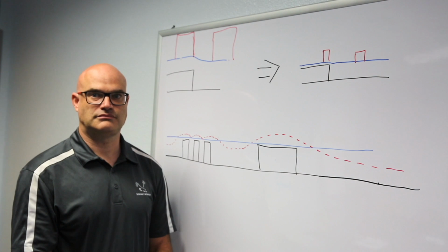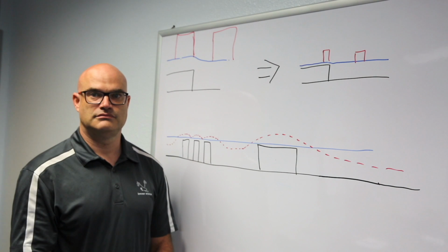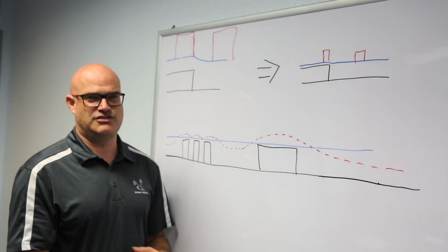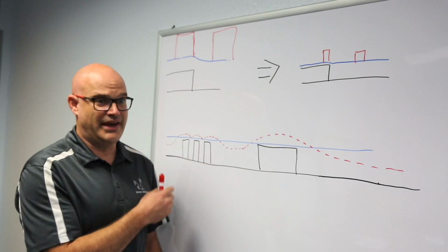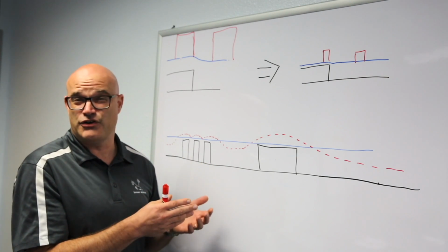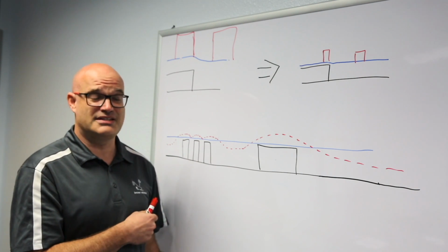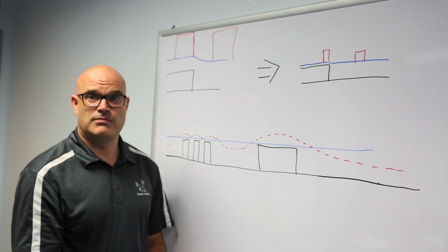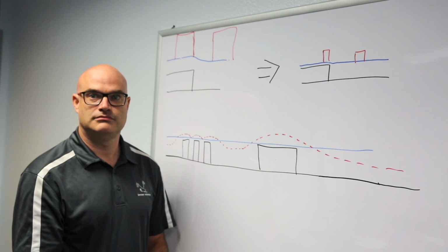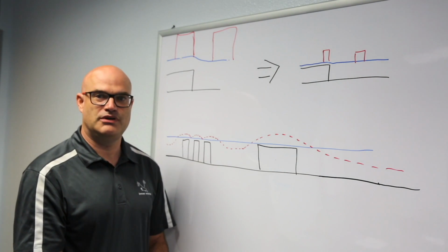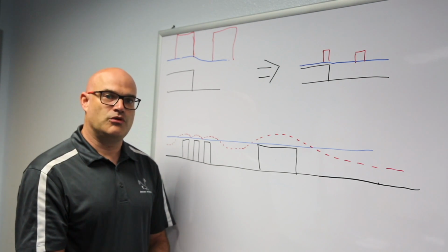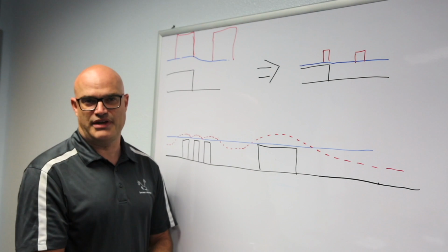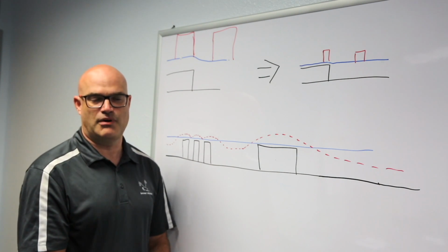What sort of material challenges are we looking at for upcoming nodes, 7 nanometers and beyond? Well, we're really looking at processes going to higher and higher temperatures. So materials have got to be able to withstand 350 to maybe 500 degrees C for maybe extended periods of time. And do you always know where those materials are going to be used? We don't always know where they're going to be used. We expect in a lot of cases these are CVD applications where the material has to be able to withstand high temperatures in the CVD process.